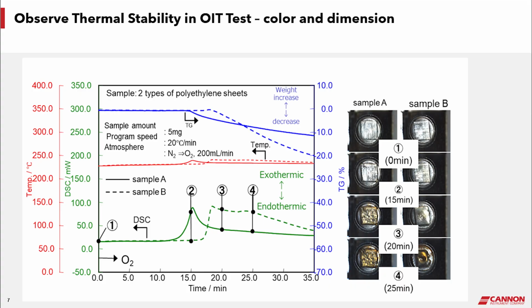And so we're plotting weight. Okay, so air is switched over to here, I should say oxygen at time 0. And in the case of DSC, which is this green curve, this green axis, we're looking at the onset of the oxidation induction time. So the deviation from the baseline is the OIT, and we can clearly see that there's a difference between samples A and B in their OIT. We could see that there's a difference in their weight profile as well.